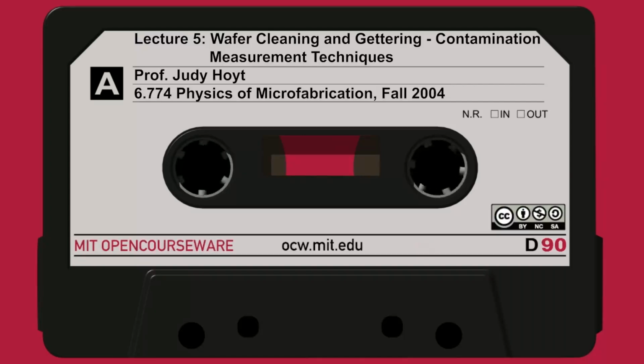Both of these effects are going to put the silicon in tension, so the silicon wafer at the surface is sort of being pulled by the oxide, which is being compressed. So if you were to grow an oxide on both sides of a wafer and strip it off the back, the wafer would actually be slightly bowed. Just ever so slightly, nothing that you could see by eye, but you can measure it in a special laser apparatus called a wafer curvature measurement. So there are ways of detecting the amount of stress just by measuring the curvature of the wafer when you remove the oxide from one side and leave it on the other side. That's how people determine some of the stress.